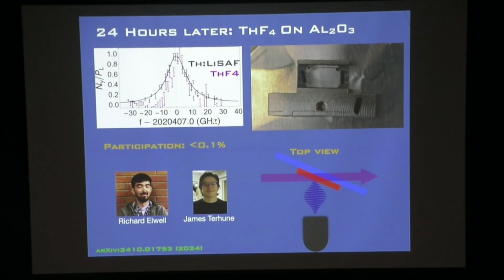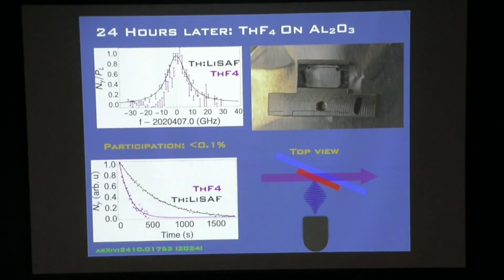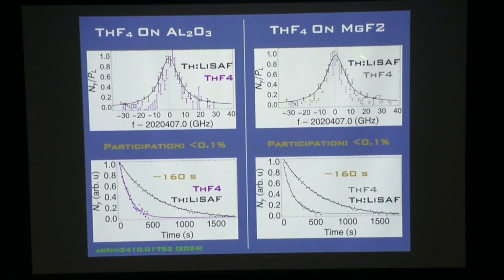Now you will notice that the signal to noise is terrible here, and the participation fraction, the amount of thorium that should contribute that actually does, that ratio is less than 1/10%. That probably sounds reasonable for such a thin film. The lifetime is also shorter in this sample. We expect it to be a little shorter because of the index of refraction, but not a full factor of 4, so that's a little bit of a mystery. When we do this on the MgF2 substrate, we see the same thing.